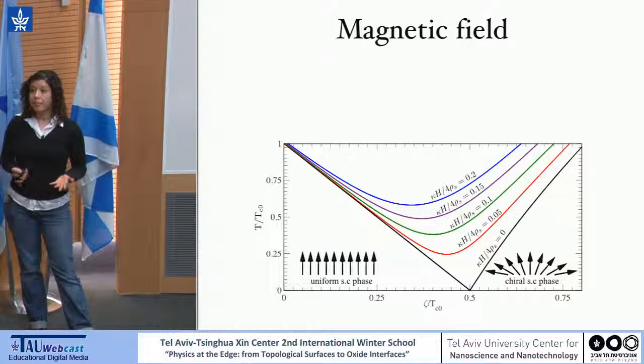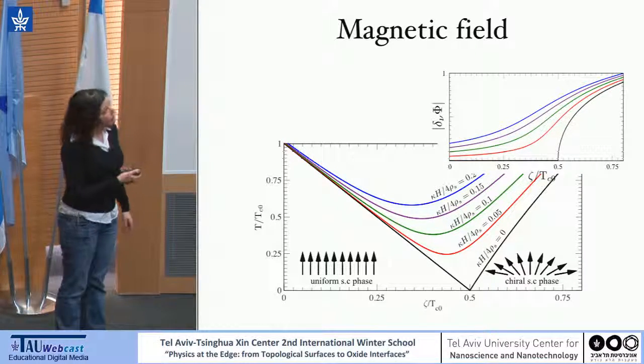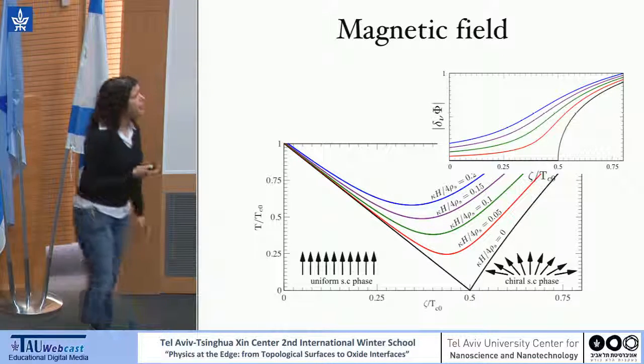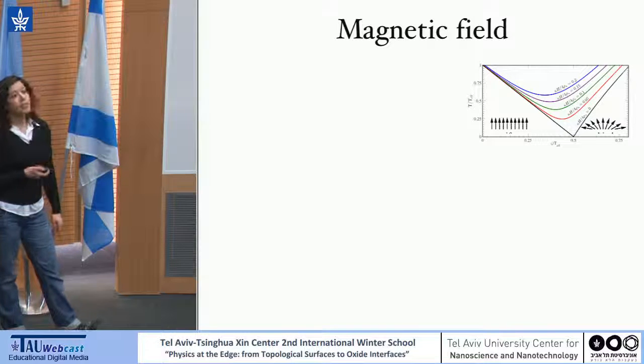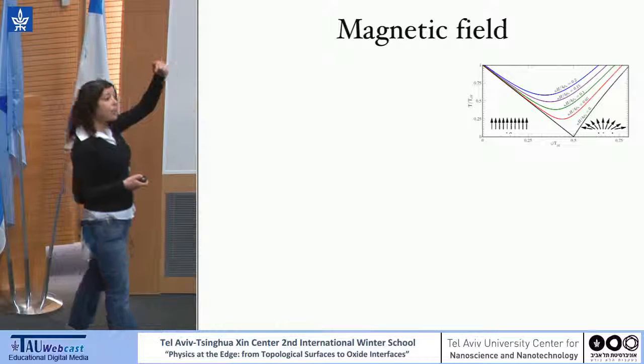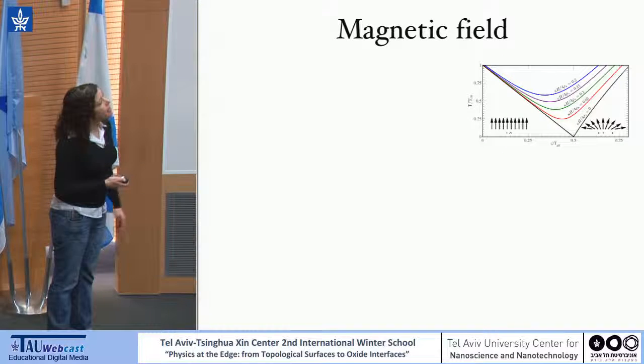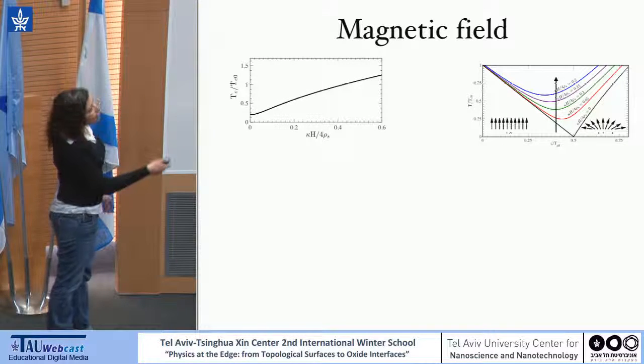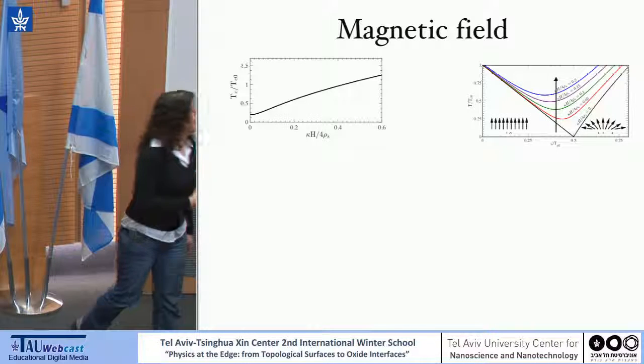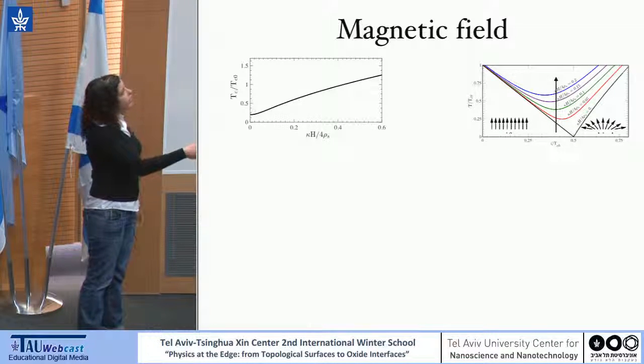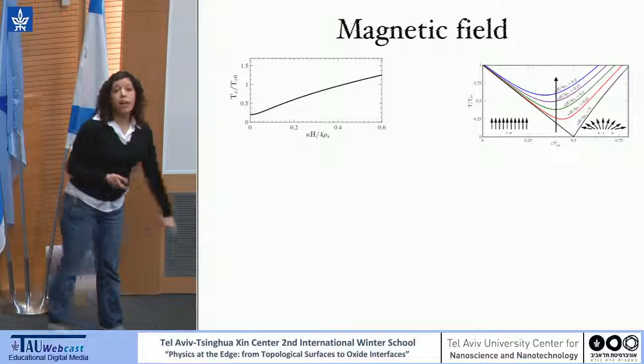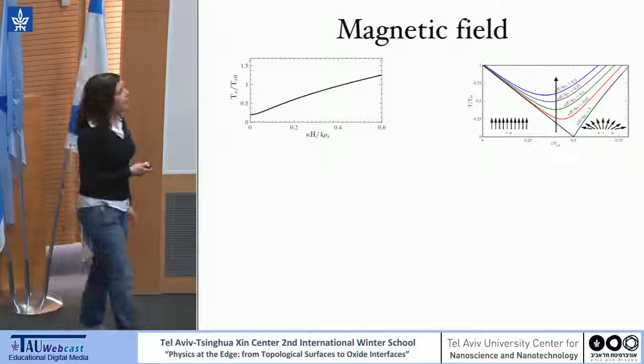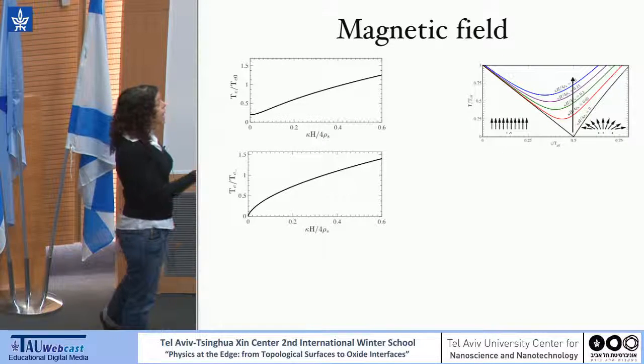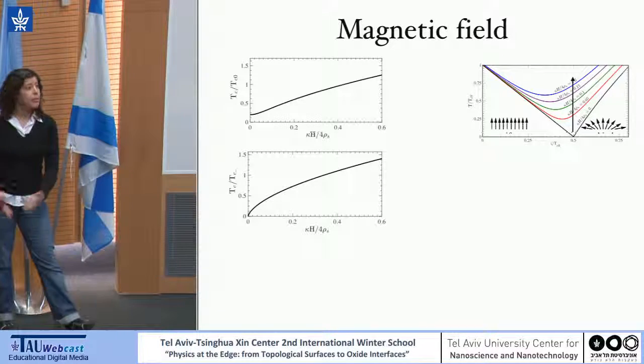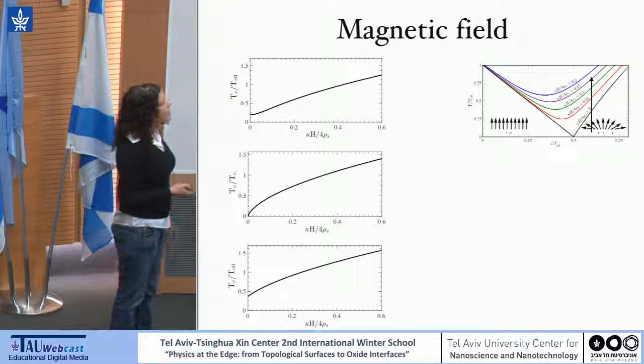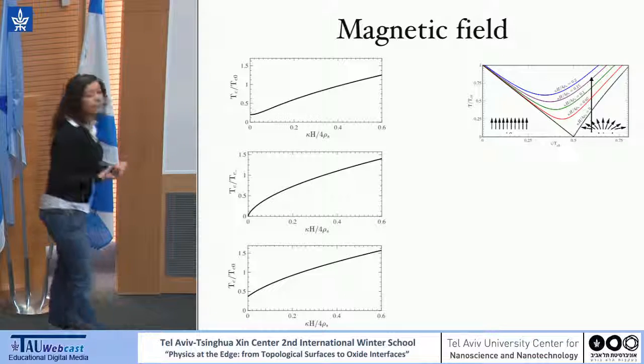And what we see here is that the magnetic field is going to lift the transition and increase the phase stiffness of our system. So we can see how the magnetization will change for different magnetic fields, but if we look now at different regions and ask how Tc changes as a function of magnetic field, for example, for one parameter here, this zeta over Tc equals 0.4. So before the transition, we can see that Tc grows as a function of magnetic field. If it will be exactly at the Lifshitz point, we can see a large enhancement in the magnetic field, basically from 0 to some finite value. And also on the other side, we can see some increase in the critical temperature.